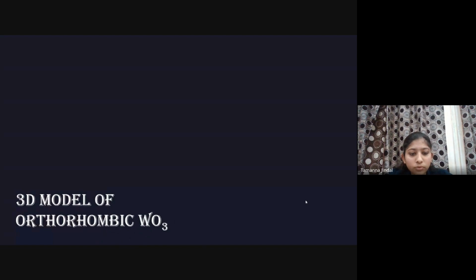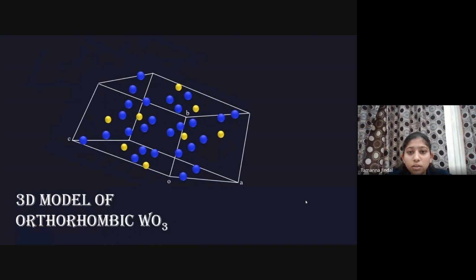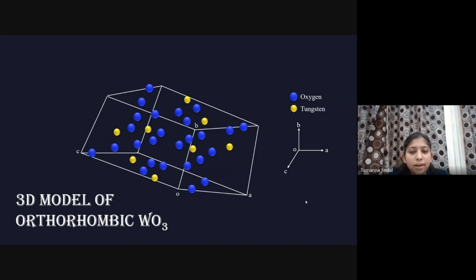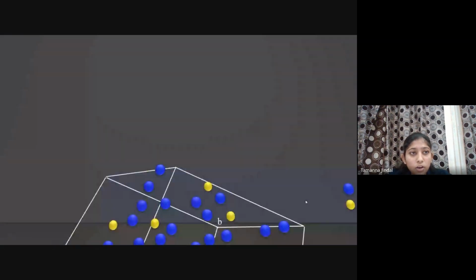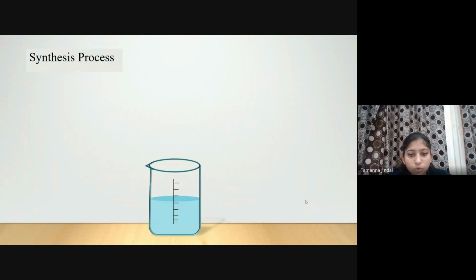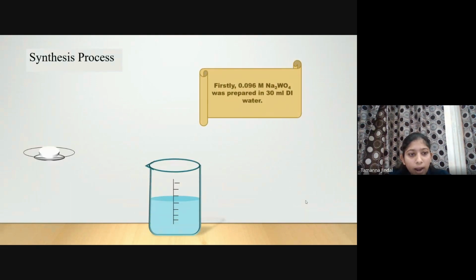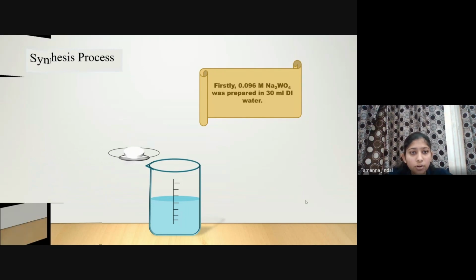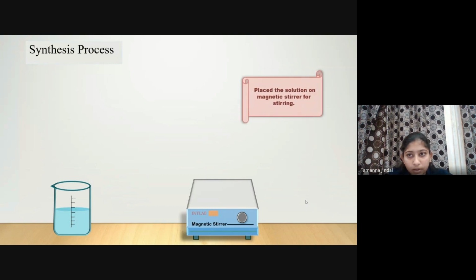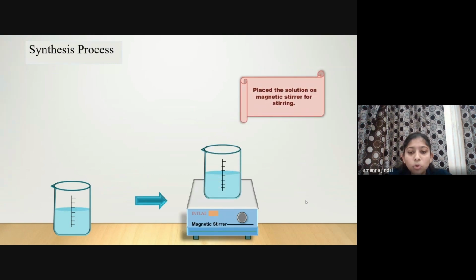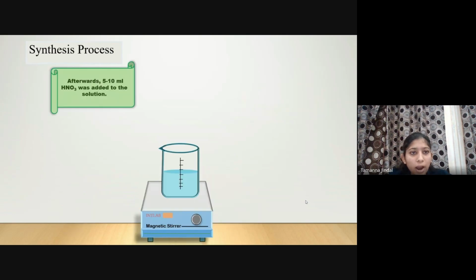Next, there is a 3D model of orthorhombic WO3, where the blue atoms represent oxygen and the yellow atoms represent tungsten. Now I am going to the synthesis process. Firstly, we took a beaker with 30 ml of DI water and added 0.096 molar Na2WO4, sodium tungstate, into it. After that, we put the beaker on the magnetic stirrer for about 30 minutes. Then we moved to the next procedure, and 5 to 10 ml of HNO3 was added to the solution dropwise and also stirred for 30 minutes.